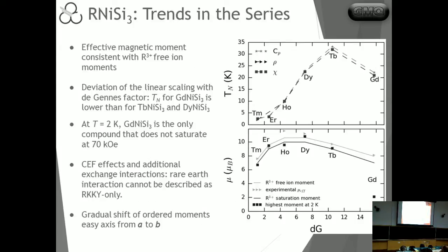Then from here we can look at a lot of trends and see how these things follow along the rare earth series. One of the things that we can look at is whether or not it follows the de Gennes scaling. In this case, it clearly does not follow the de Gennes scaling. And one thing that becomes clear is that the gadolinium actually has a very anomalous behavior in the system because it has a lower ordering temperature than terbium. And this is just something that's quite rare. You just don't see that.